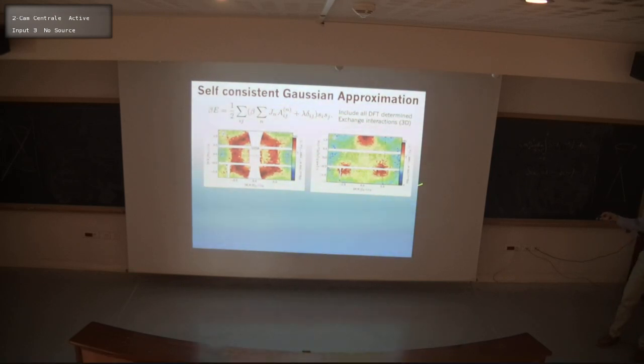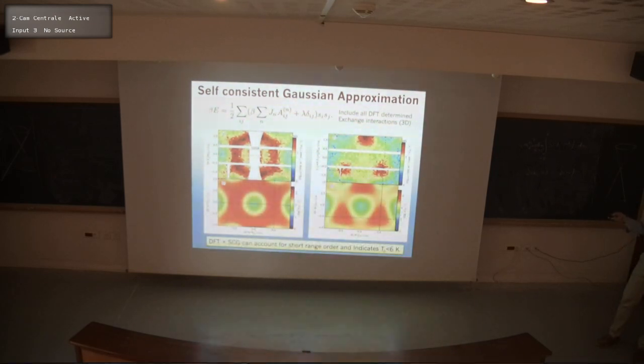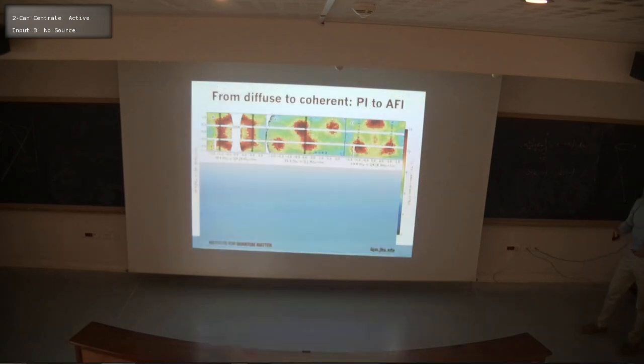And so this is the measurement, and this is then the calculated dynamic correlations that you would somehow expect based on these DFT results. So it's kind of quasi-ab initio, not ab initio because U was put in by hand, and also because we had to use this approximation. This approximation should be okay because we are working at very, very short correlation lengths. So somehow it actually can account for the data quite well. And so there's something frustrating in this structure.